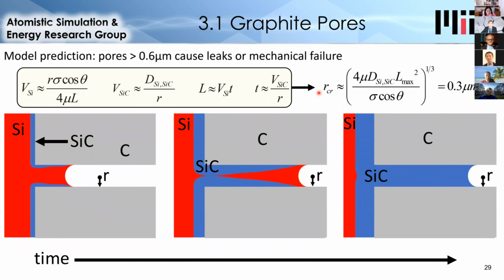Now, the first question we want to answer with regard to these experiments is what is the effect of graphite pores, and specifically the effect of pore size? So first I wanted to try to estimate this effect. And I did this with just a simple mathematical model comparing the driving force for silicon to leak out of a pore, which is shown in red, to the reaction of silicon carbide, which is closing the pore.